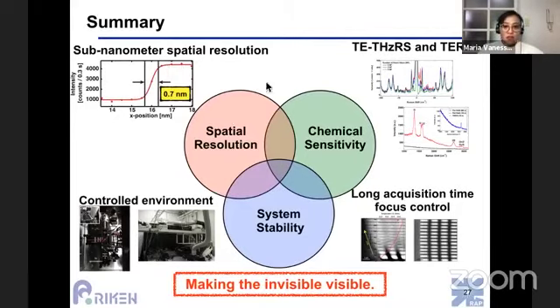And so far, using the STM, we are able to obtain the sub-nanometer spatial resolution, which in turn can unlock certain Raman modes, which can in turn also increase the chemical sensitivity of our system. But all of this, or these two, of course, should go hand in hand with high system stability. Without the high system stability, we cannot get reproducible and reliable results.